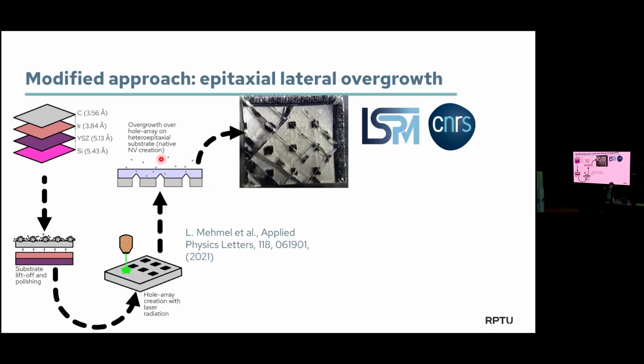And when the diamond is growing into these holes, it's not attached anymore to that bad diamond, and it can release some stress, for example, during the growth. And this is how the sample really looks like. These are the holes, no? And on top, you have this newly grown diamond. Please don't get scared. The sample is not broken. These strange lines are growth steps that can happen during the growth of the diamond. I have been told, yeah. I first also thought it was broken, but it isn't.